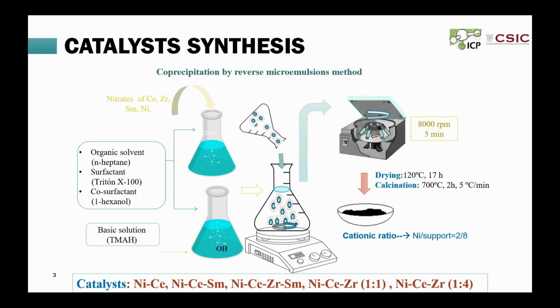Our catalysts were prepared by the co-precipitation method using two microemulsions, an acid one with the precursor salt dissolved and a basic one, to achieve greater homogeneity and surface area. And the cationic ratio of nickel to support that we used was 2/8.